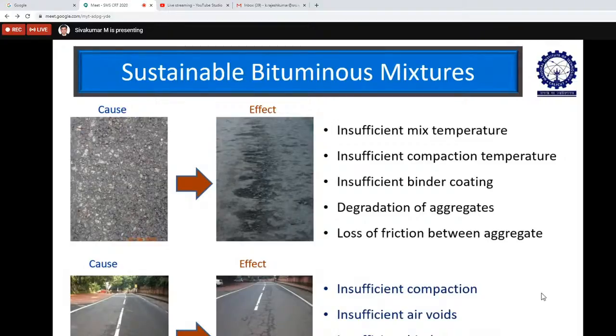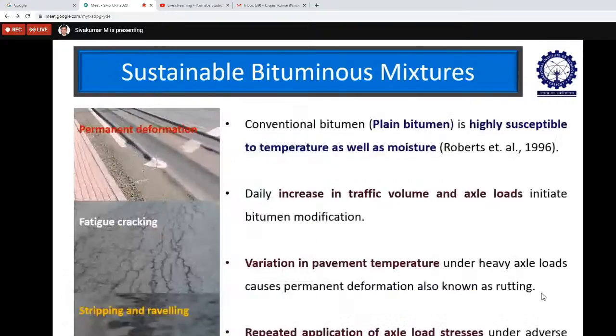Next, suppose there is insufficient compaction or insufficient air voids. Compaction should be sufficient, but at the same time, it should not be over-compacted. Then it will become insufficient air voids, and it will lead to this kind of cracks on the pavement layers, that is, longitudinal cracks from the top down. Mostly, if the cracks are structural, then they will be progressive cracks, leading to pavement deterioration. So these are the major problems which we face in bituminous pavements.